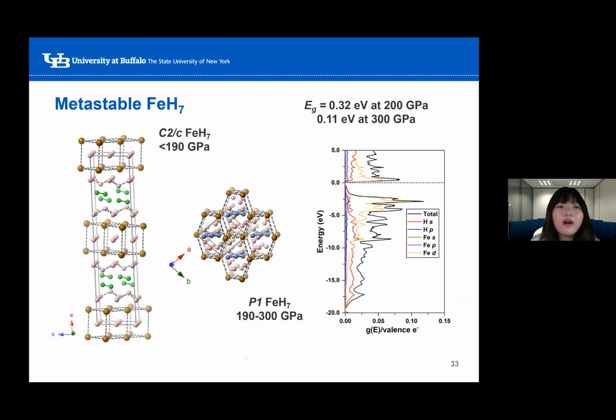For FeH7, we found a C2/c structure stable up to 190 GPa. It is very similar to FeH6, comprised of FeH3 layers separated by atomic and molecular hydrogen layers. At higher pressure, up to 300 GPa, we found a P1 FeH7 phase that looks different, but is actually similar to the known FeH6 structure that's above 200 GPa. It is comprised of iron three-dimensional networks extending along the c direction. The difference between this FeH7 and the known FeH6 is that the channel shape is different, and it contains H3-minus-like units shown here. This structure, however, is non-metallic at 200 GPa and 300 GPa.